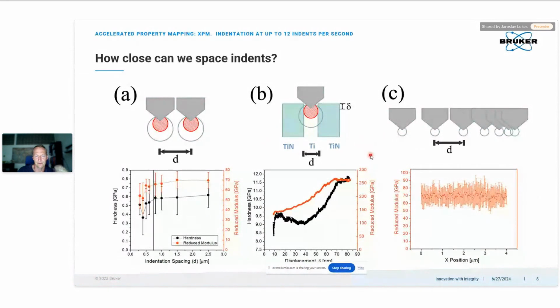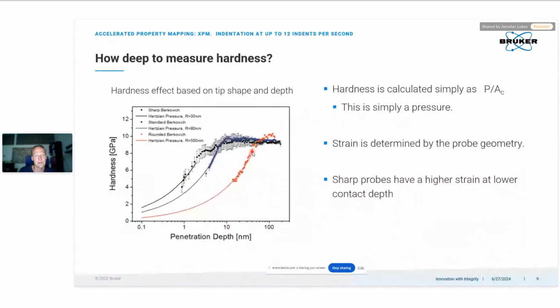So let's say the takeaway message from this slide is the indentation spacing and the depths that you want to produce. The smaller the indentation depths, the smaller the spacing can be, and the higher the resolution of your map. But since hardness depends on the plastic deformation, you also need to take into account the geometry of your probe. So this is also a very influential parameter.